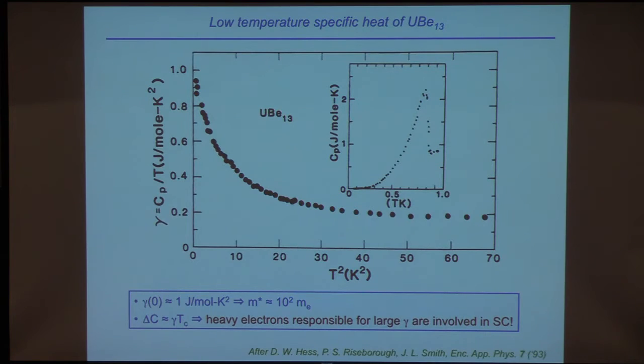And then the susceptibility becomes finite, indicating that you have a non-magnetic ground state. And then the most dramatic thing is C over T, or the electronic specific heat coefficient, plotted here versus T squared. And you see that it rises dramatically up to a value of about 1 joule per mole Kelvin squared at low temperatures, corresponding to a very large effective mass. And then this also becomes superconducting.